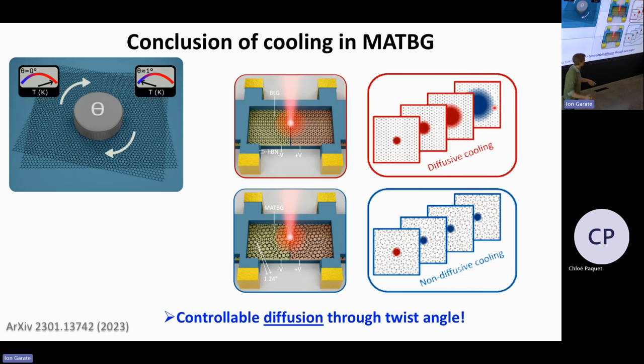Another aspect of this that's interesting is that you're not only changing the energy dynamics, but also the spatial dynamics. Because what's happening, in fact, in the non-twisted sample, is that because the coupling to the phonons is so slow, there's a different relaxation or cooling mechanism that takes over. And this is diffusive cooling. So basically what happens is that you shine light in a small spot. This cannot release its energy to the phonon system, so the spot just starts broadening, and by that it cools down. So this is something we call diffusive cooling, and that's something that happens for this non-twisted sample.